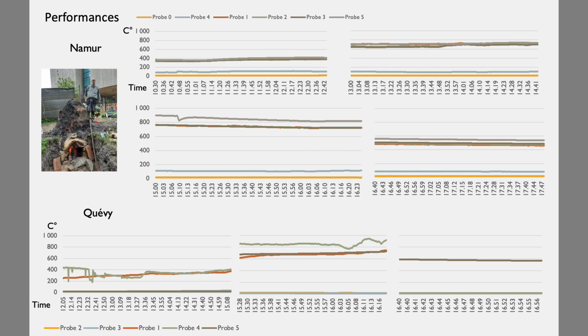In the kiln from Namur, the temperatures were easy to control. Their rise was low, regular and quite homogeneous. In less than 5 hours, the kiln reaches 900 degrees. The kiln was then closed with tiles, and only 1/8 of a stère of wood was needed for the firing.